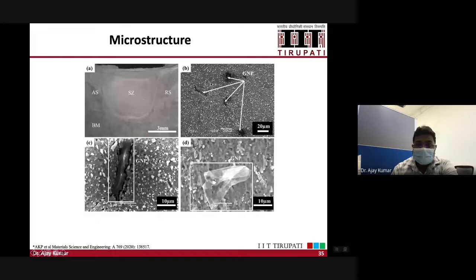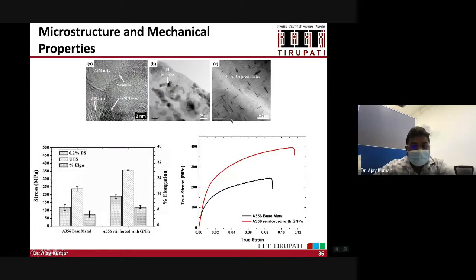And then you do the microscopic study to find out whether these nanoplatelets are embedded inside the matrix. As you know, A356 is a silicon based alloy. So this is the GNP, the graphene nanoplatelets, which is embedded inside the matrix. And you will also see the fine silicon particles. When we conducted the transmission electron microscopic study to understand at the nanoscale, we saw the aluminum matrix and the GNP flakes, and there is no defect at the interface, and the silicon particles were reduced. We have also seen a significant increment in the strength as well as the toughness of these materials.